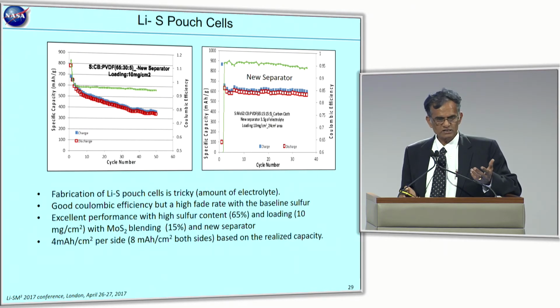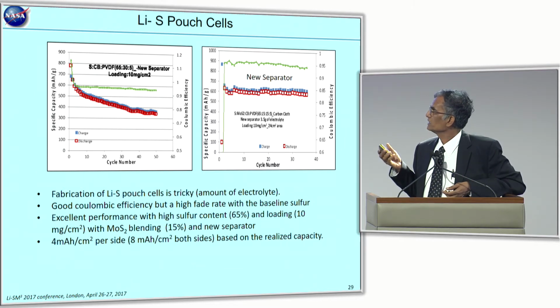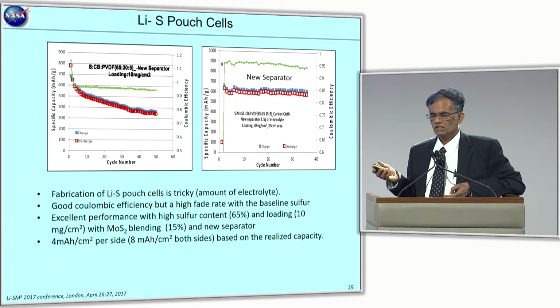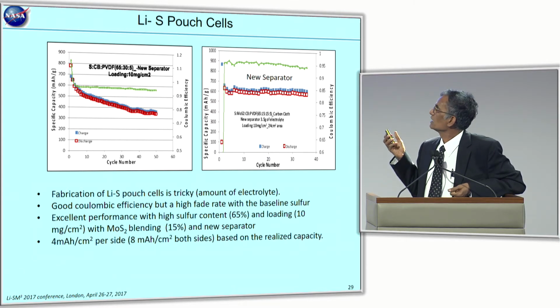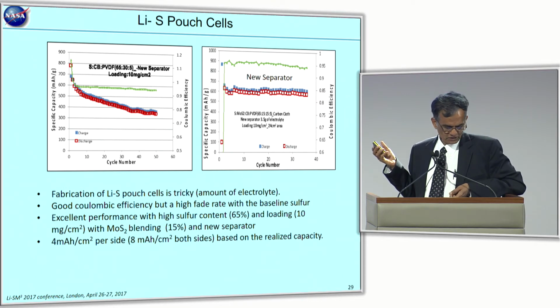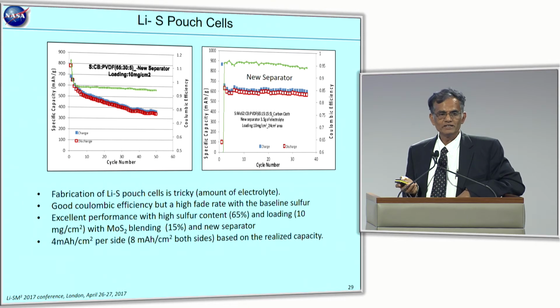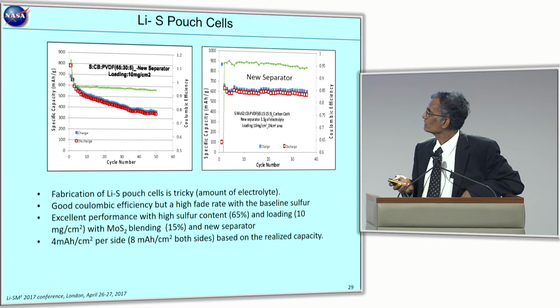Combining these metal sulfide blended cathodes with this separator, we have seen a clear difference between the baseline cathode on the left without any metal sulfide, and the one with the new ceramic coated separator. We have seen good performance here. And keep in mind that we are talking about a fairly high current density, 8 milliamperes per square centimeter here.